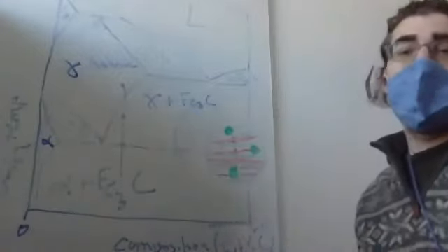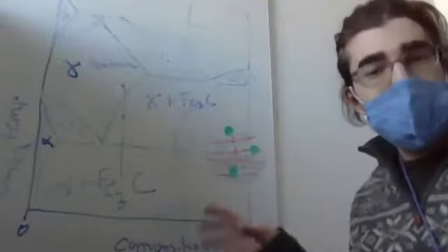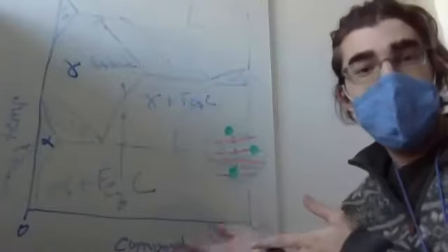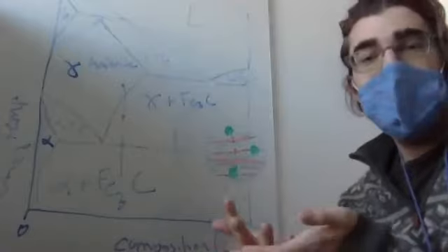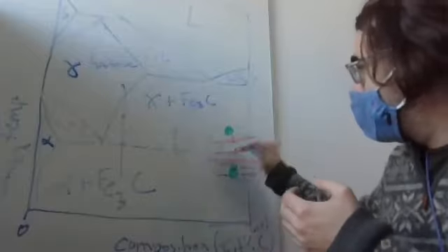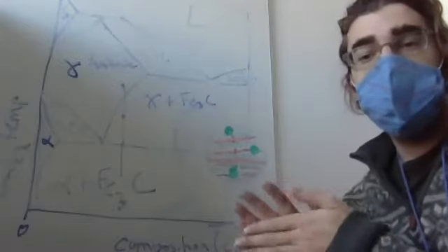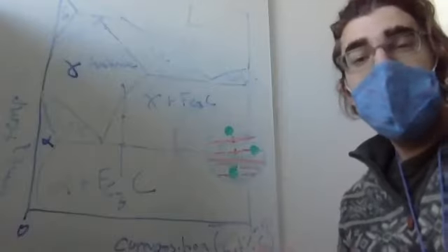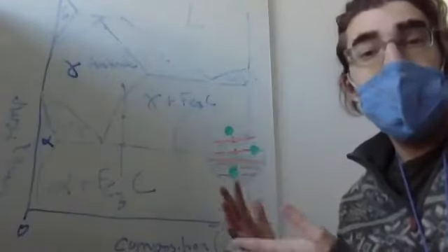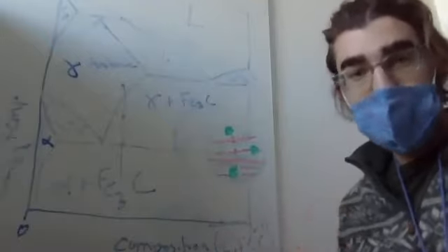And this looks very similar to precipitation hardening, right? So we precipitated out a phase, the cementite phase, and we got these little grains, great. And then when we continue to cool the material, we created this layered structure again, but with the ferrite crystals still intact. And in this way, we generate a material that will have a higher hardness, right? It'll be more hard because we have more of a hard phase present.